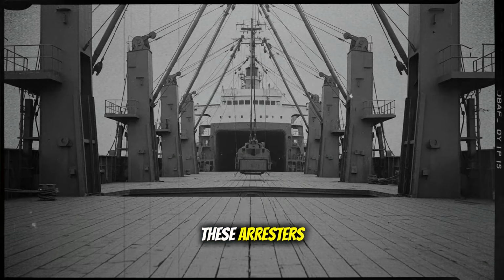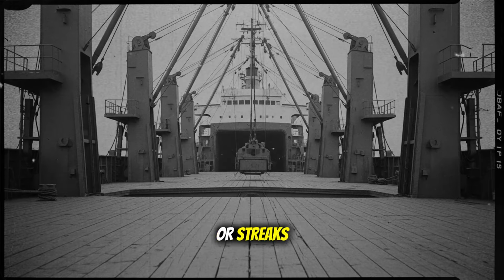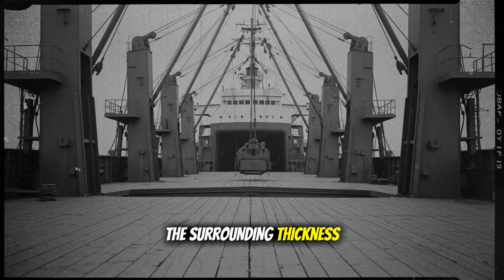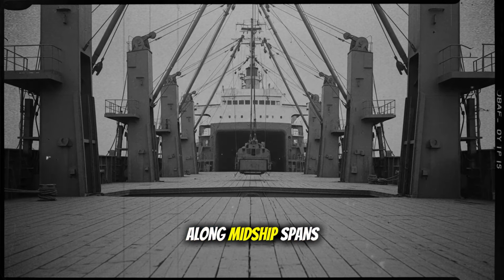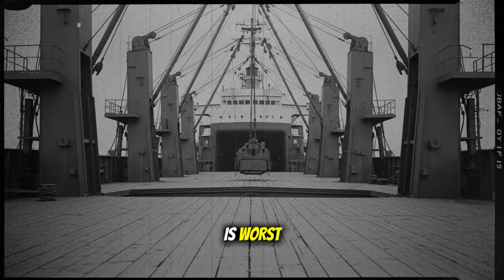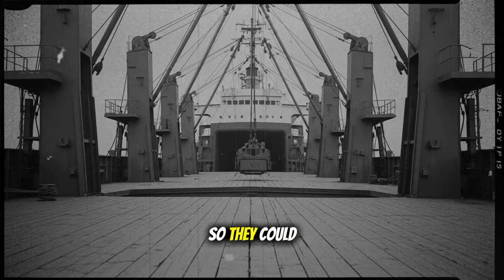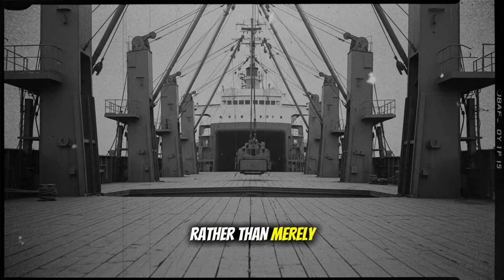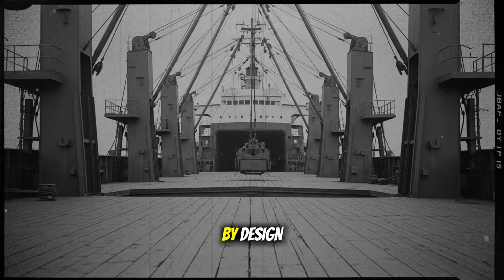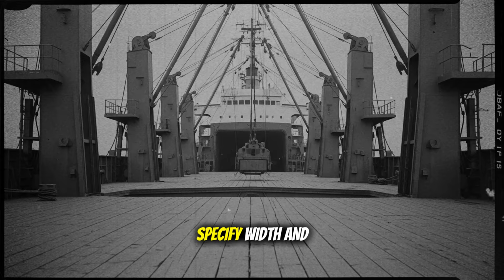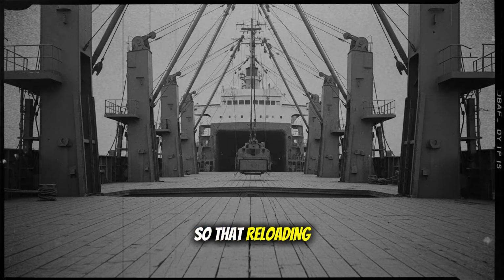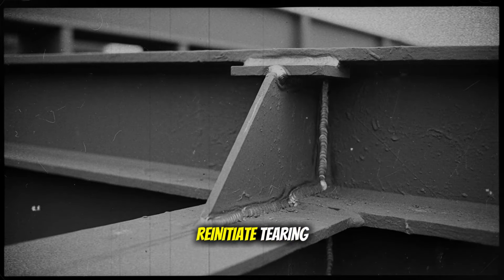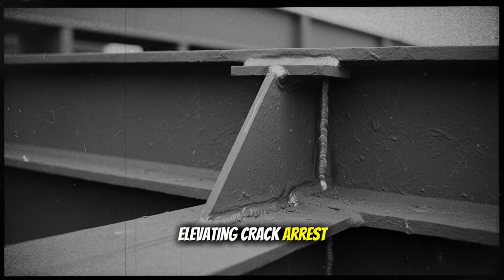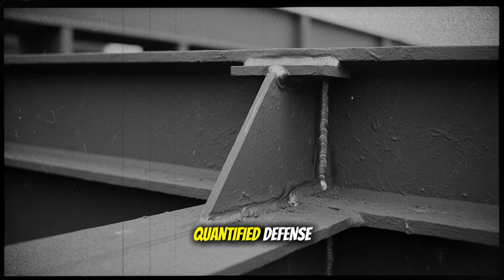These arresters, typically in the form of plates or strakes embedded to match the surrounding thickness, were placed strategically along midship spans where global bending is worst, sized and located so they could halt a moving crack rather than merely watch it pass by. Design guidance matured to specify width and arrangement so that reloading after arrest would not simply reinitiate tearing, elevating crack arrest from a hopeful detail to a quantified defense written into the ship's backbone.